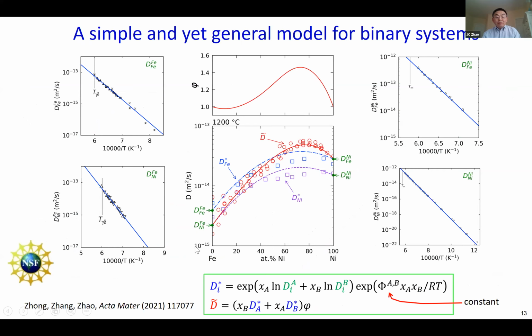Basically, it's the pure elements data on both sides, and then how do we fit the interdiffusion and the intrinsic diffusion coefficient? We developed a model with only one fitting parameter, one fitting constant, to be able to describe the behavior of binaries. I think this will simplify a lot of things for the future.